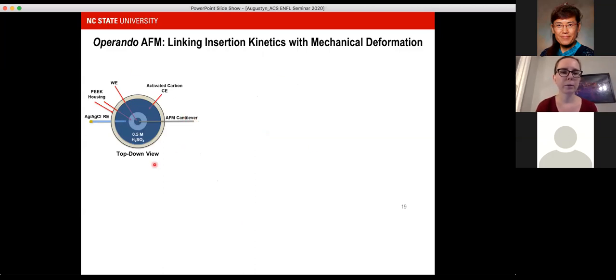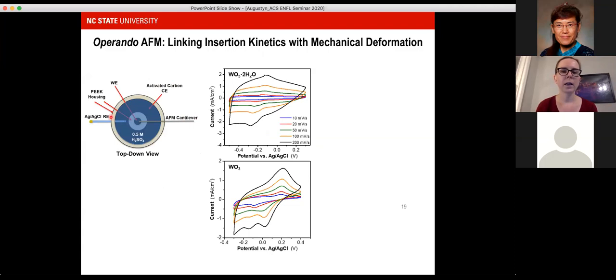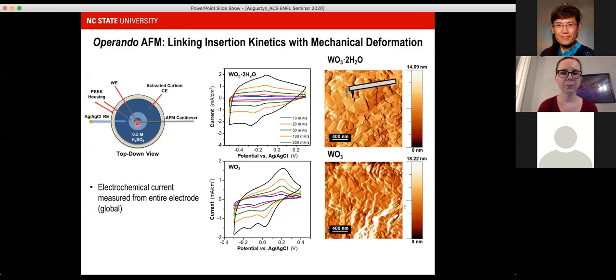This is an in situ AFM cell, so this is how it looks. Our electrochemistry looks very similar as before, so more reversible cyclic voltammograms for the hydrous material, less reversible for the anhydrous material. We measured the electrochemical current in this experiment from the entire electrode that's sitting here, but the AFM response that we measure is coming just from a very local measurement of the deformation or the deflection of the AFM tip in a position where we land on top of our electrode. So this is what the surfaces of our electrodes look like. They're similar, these platelets, there's just platelets and some polymer binder there. There was no carbon. And then sulfuric acid flooded throughout.